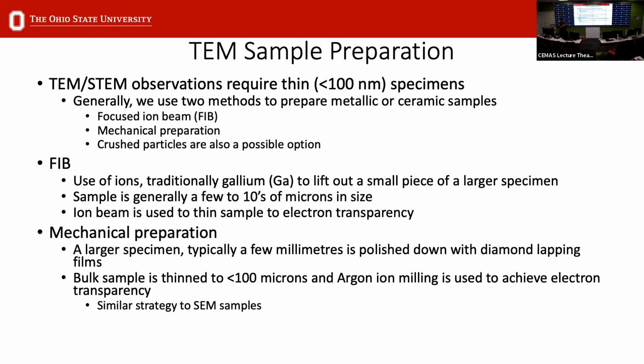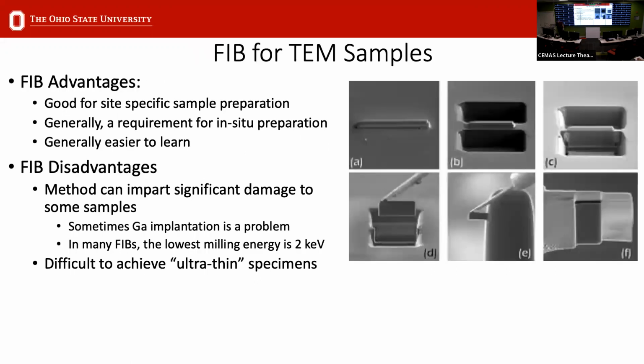With mechanical preparation, you then use the sectioning that I mentioned earlier. You would cut a piece of your sample that's usually on the order of 1 to 2 millimeters by 1 to 2 millimeters, and you would progressively polish this down to under 100 microns and use something like argon milling to achieve electron transparency. And I'll go into a little bit more detail about that.